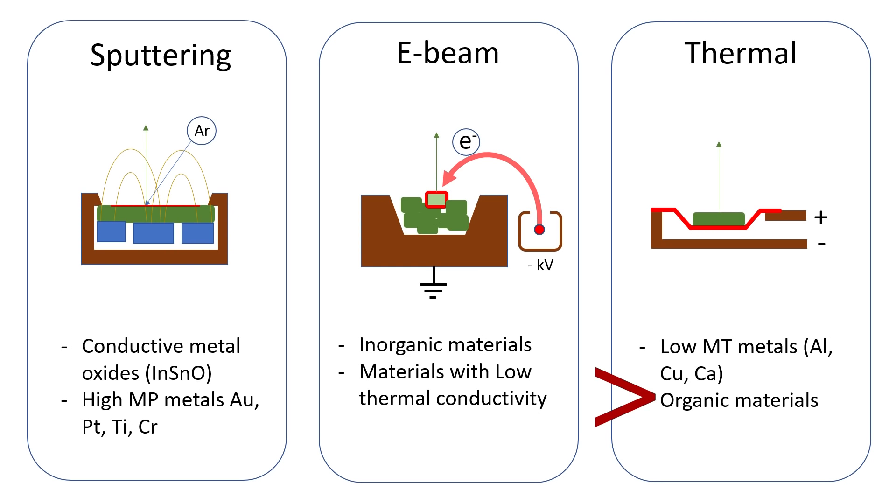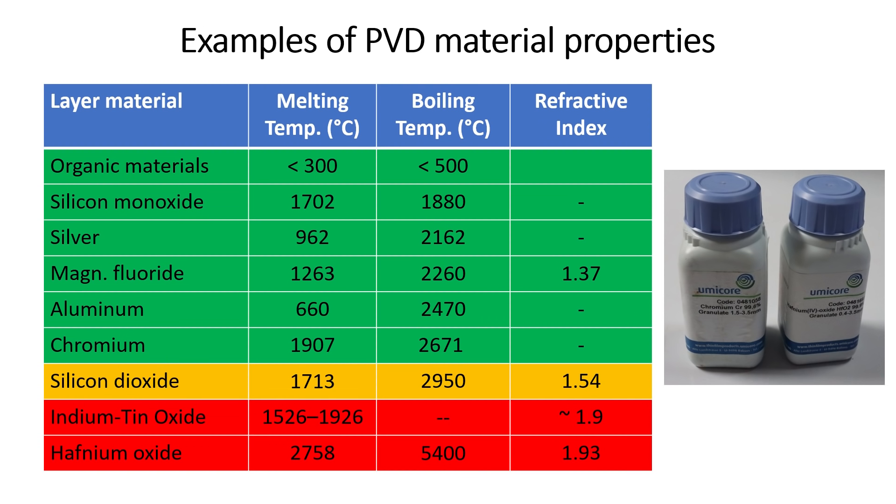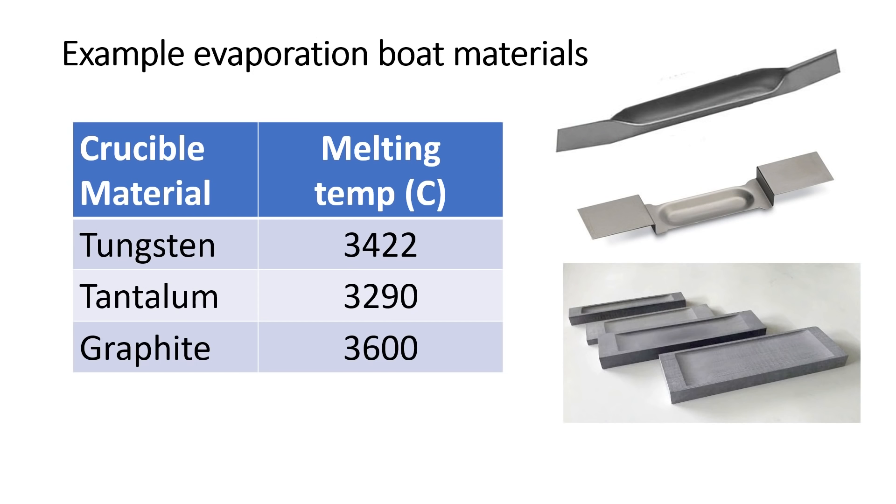However, thermal evaporation has a few limitations, mainly because of the temperature range for which it can be used. Here is a table with some of the materials that I have been planning to deposit. It shows several materials in green, which should pose no problem for thermal evaporation. But for the ones in orange and red, we require higher temperatures than what you can comfortably achieve with thermal evaporation, either because they have too high a boiling point or because they are very bad conductors of heat.